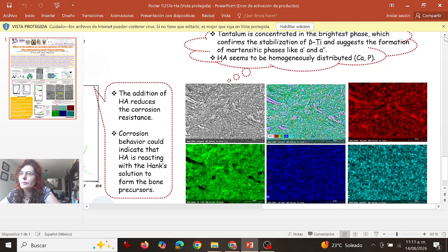And what we can see is that the tantalum is concentrated in the brightest phase. If you're talking about the tantalum in here, in red is the tantalum. So the tantalum is concentrated in this, as we can observe, the brightest phase, which confirms the stabilization of the beta titanium and suggests the formation of martensitic phases like alpha prime and alpha double prime. So alpha prime and alpha double prime are martensitic phases of the titanium that are formed when the beta phase of the titanium rapidly gets cold.